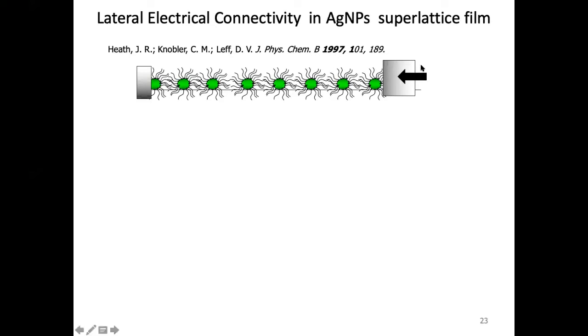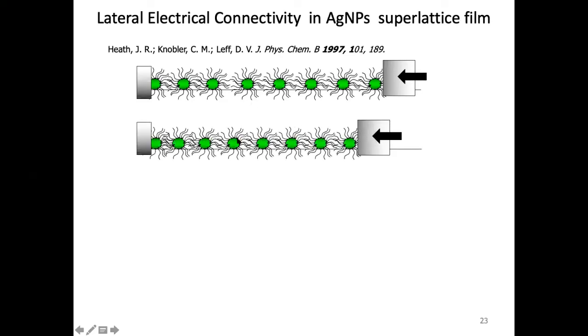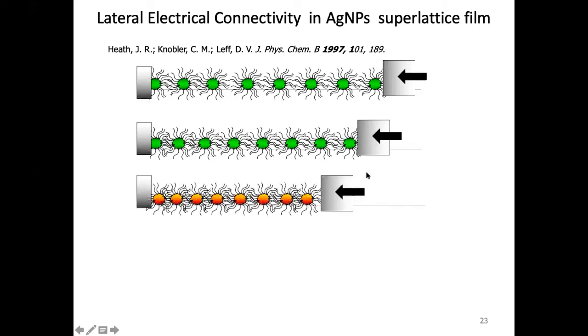Now I have one interesting part here. It's a slider in a Langmuir-Blodgett film. I can now compress this film by applying pressure from this side. So now my film is getting compressed, which means what? I'm bringing the particles close to each other. Here the particles are away from each other. There's no contact between one particle and another. So if you try to measure the lateral conductivity of this film, it is insulating. But if you start compressing it enough, the particles become quite close to each other. Then what will happen?